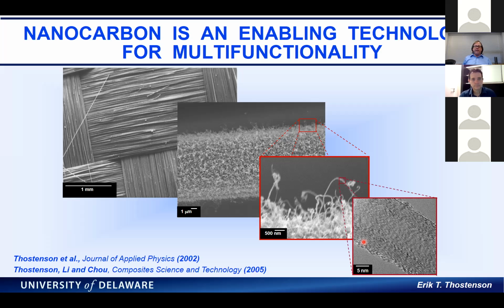in general. It doesn't have as high sensitivity in terms of piezoresistivity. We haven't spent a lot of time looking at it, but I suspect it's because it depends on how these sheets contact each other, whereas the tubes really contact each other at a single quantum tunneling point. With the sheets you might have multiple contacts between individual sheets, and that essentially shorts it out. That's just a hypothesis. We haven't really investigated that much, but I could say at similar volume or weight fractions, you'll see that the nanotube sensors tend to have higher sensitivity.